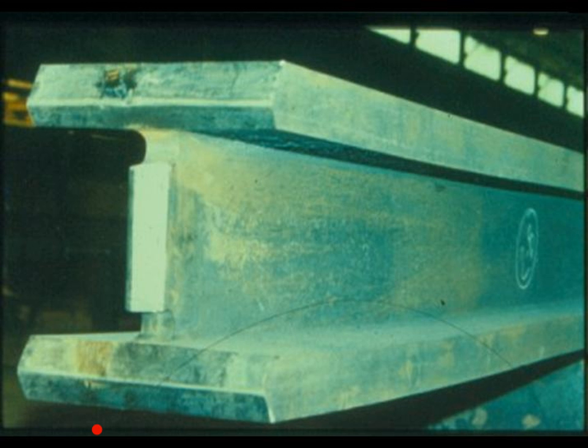The answer is yes, it still can be. I'm pleased to say that lamellar tearing problems in 2009 are much less than what we experienced through the 70s and the 80s. That in part is change in steel mill practice. But we still do have some lamellar tearing concerns, and large welds that strain the material in the through thickness direction are always problematic issues. Now, lamellar tearing seems to be most closely associated with welds right on the edge of the plate. And so for the example that's been cited, columns to base plates, usually we have some edge material that goes out beyond the edge of the material, of course, for your bolts and so forth, and should be less of a problem than, for example, in corner joints of fabricated boxes. All right, so I hope I addressed that issue.